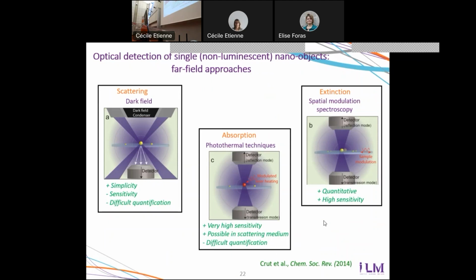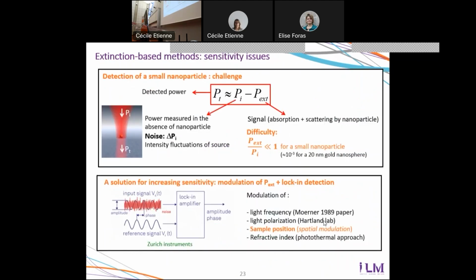And then the technique that we use in the laboratory is called spatial modulation spectroscopy. So this one uses scattering, this one uses absorption, and this one uses extinction. So it's sensitive to both absorption and scattering. And as you will see, it's a very quantitative and highly sensitive method that I will now describe in more detail. The idea behind this method is quite simple.